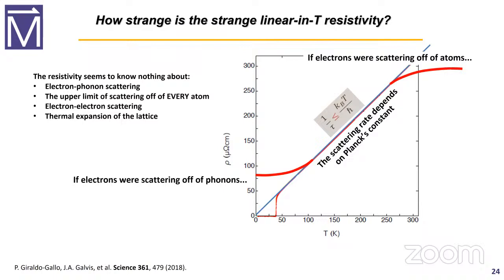But the resistivity seems to know nothing about electron-phonon scattering, nothing about the upper limit of scattering off of every atom. I didn't even mention electron-electron scattering, which would give you deviations. I didn't mention thermal expansion of the lattice. The lattice is changing, and yet the resistivity just goes straight linear with T. So these theories that I alluded to earlier are speculating that maybe the state is so quantum mechanically entangled, as is the case in black holes, that there are no recognizable quasiparticles. That it's a macroscopic quantum state where you don't have point-like excitations. There's no reason you should have them.